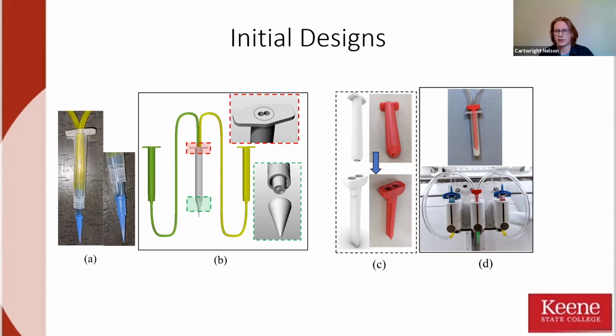And once the plungers in the syringes were at the bottom, it was unable to print, because even though there was still air pressure and material, the plungers couldn't go anywhere. So the whole thing was left full of material and had to be reloaded over and over again, which was very wasteful. It also required a lot of pressure, and the pressure would actually backflow material into the other side of the system instead of coming out of the nozzle.